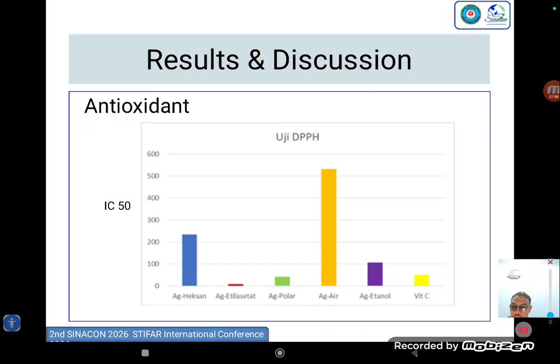The DPPH assay results reveal that silver nanoparticles synthesized using the water fraction exhibit the lowest antioxidant activity compared to other fractions, and were notably lower than the vitamin C standard. This is likely attributed to the water fraction containing a lower amount of phenolic and flavonoid compounds, which act as primary antioxidants. Overall, this finding indicates that the type of solvent fraction utilized in the green synthesis process significantly influences the antioxidant activity of the resulting silver nanoparticles.